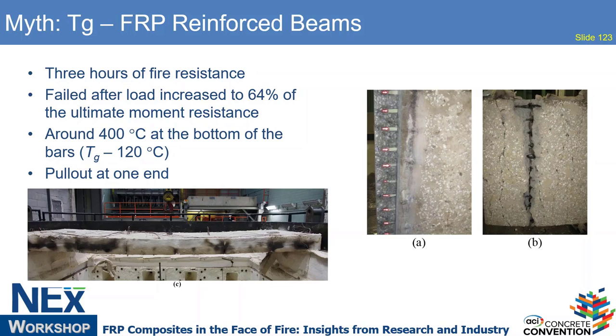This is about the pullout that we did eventually get in failure. After 3 hours, we had to increase the applied loads in order to get that failure. We had about 8 inches of slip at the end.